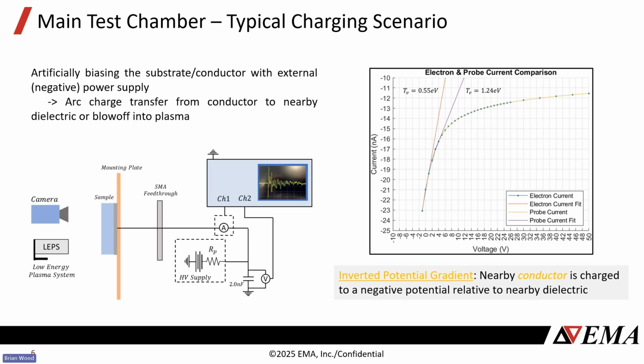There's another way: instead of using the LEPS, you can irradiate with low energy electrons and exploit the secondary electron yield of the material. And so you're basically charging that front surface more positive by just exploiting the secondary electron yield. And likewise before, for monitoring arcing in this situation, we also have the current probe in series with that signal line. In parallel with that, I'm showing a 2 nanofarad capacitor. That's put in there to help represent the capacitance that might be associated with the arc.